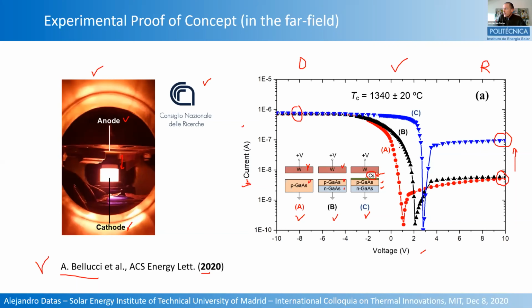But the most remarkable thing is the voltage improvement. In particular, if we look at device A and B, we see that there is an increase in the voltage. For the same current, you get higher voltage in the case where you have a photovoltaic anode. And this voltage is even higher if we use cesium on top of the photovoltaic cell due to the reduction of the work function. So this represents basically the proof of this concept.